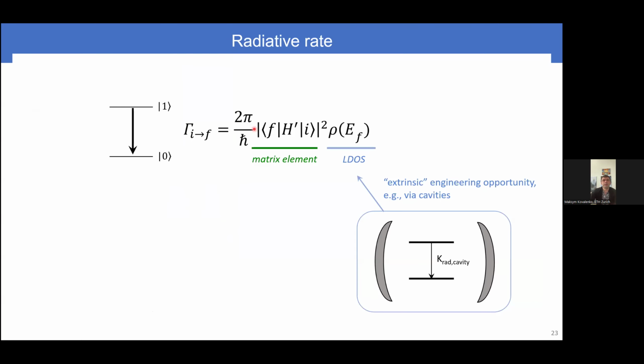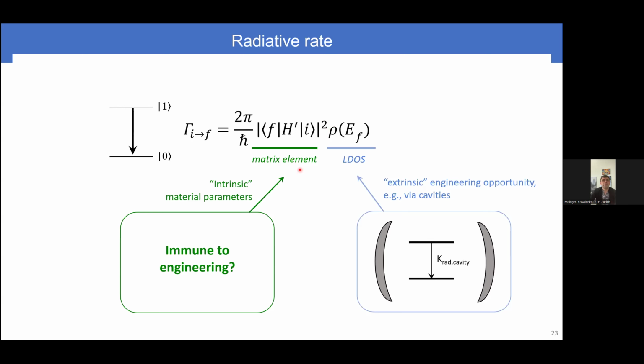And so when you look at the golden Fermi rule, you know that the rate of your transition, so the T1, will scale with the intrinsic property, which is the oscillator strength of your transition, and the local density of states, which you can engineer by external cavities and things like that. That's what people do with epitaxial dots these days. We are not there yet to engineer those extrinsic factors. But what we will look at is the intrinsic oscillator strength of these emitters. And typically, you would imagine that this should be sort of constant. It's a property of that specific material.